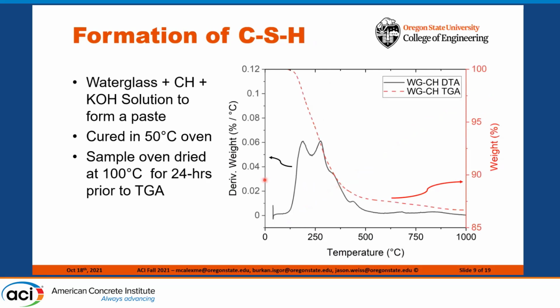To experimentally back up the thermodynamic modeling, we created a paste using water glass, calcium hydroxide, and potassium hydroxide solution using the same ratios as in the model. We then cured it at 50 degrees Celsius in an oven for 7 days, then stored at room temperature until we ground it into a fine powder. Oven dried it for 24 hours at 100 degrees Celsius to remove the water, and then ran it through the TGA. This graph shows the weight loss curve and its derivative here.